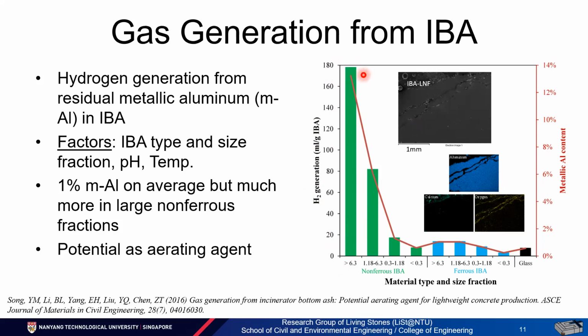Because even going through the incineration process, due to the high ductility, the metallic aluminum is not easily broken down into smaller pieces. With such high gas generation potential, we'll say it's about 10 times - you can see here it's more than 10% of the metallic aluminum in the larger particles.